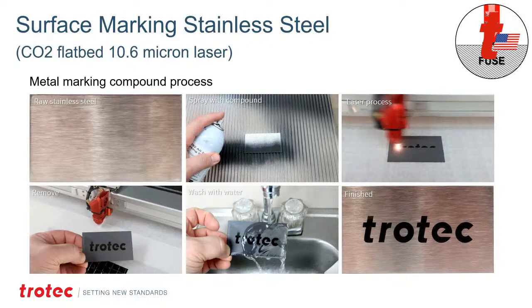It's a clay-based compound, a molybdenum disulfide type sandy material, and so you can wash it right down the drain safely. And then once you're finished, you're going to actually have that fused mark, and that finished fused mark is a high contrast. If you look under a microscope, it actually looks like little beads of glass have been melted to the surface of the metal, and that's in essence what it is. So this is an extremely popular process. It doesn't require the additional cost of a fiber laser or a Galvo fiber laser.